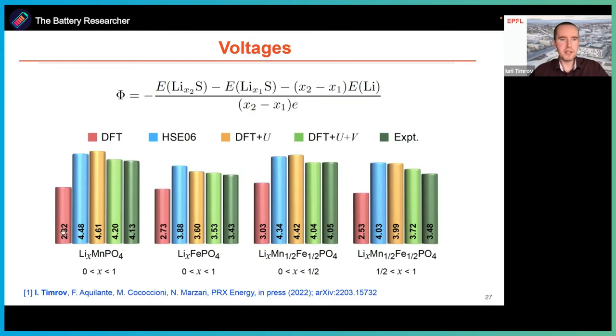And these are the results, which, by the way, are recently in press in PRX Energy. Here we see that DFT systematically underestimates voltages, while hybrid HSE06 in blue corrects it, but too much. DFT+U, similar to hybrids, gives too much of a correction. And the best agreement with experiment is obtained really when we use DFT+U+V. So the error between experiment and our best DFT+U+V calculations is of the order of 0.1 volt, which is quite remarkable.